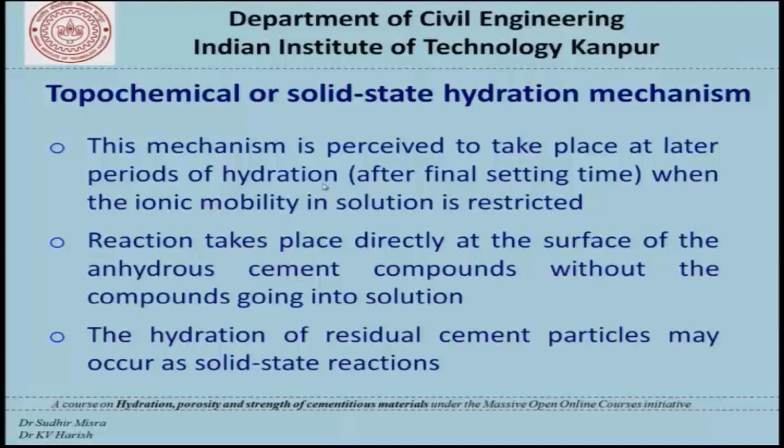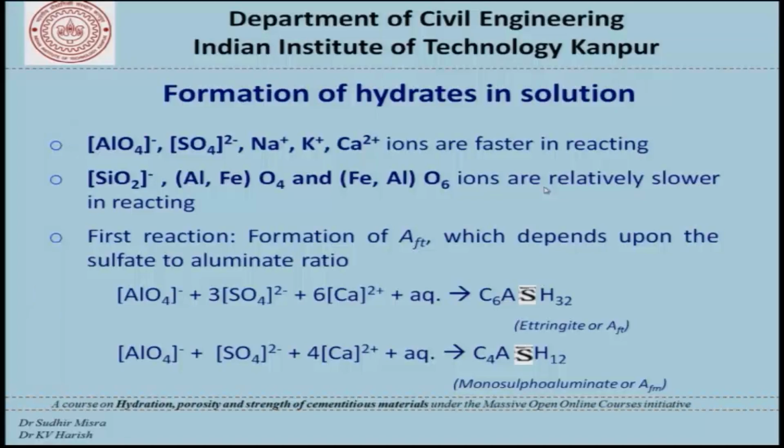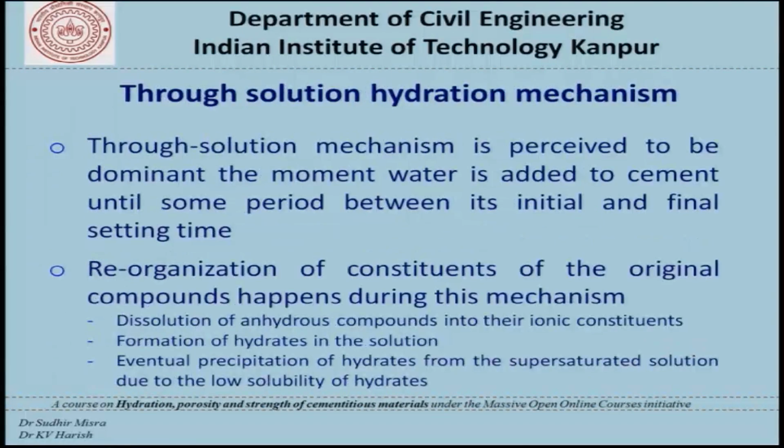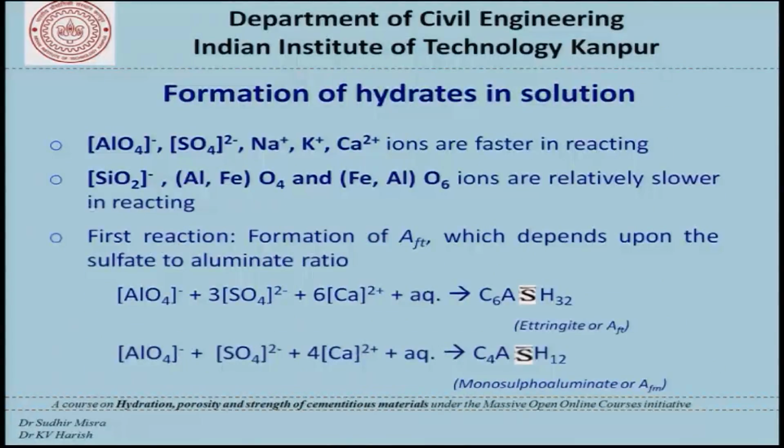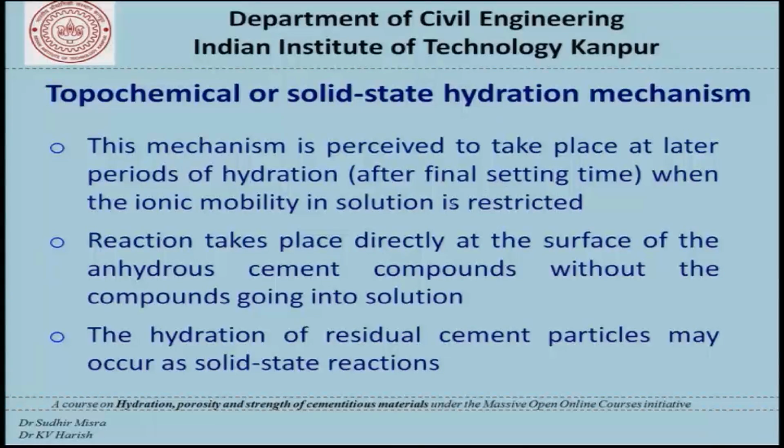This mechanism is perceived to take place at later periods of hydration, that is after final setting time. Remember that in the case of through-solution hydration, it is explained to take place from the time water is added to cement to its initial setting time or final setting time. So, in this case it is what is happening after final setting time. Reaction takes place directly at the surface of anhydrous cement compounds without the compounds going into solution.